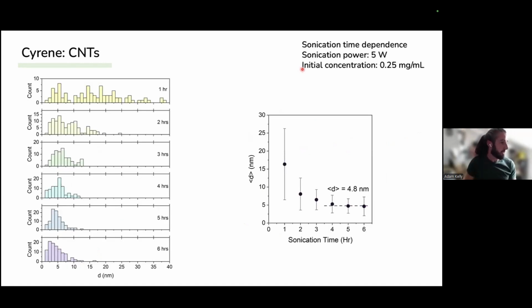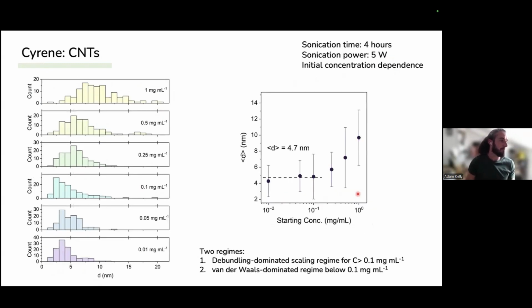So we did a sonication time dependence where we used the same sonication power of 5 watts, and we held the initial concentration constant at about 0.25 mg per mL. We can see as we go up from 1 hour, 2 hours, 3 hours, up to 6 hours, that the distribution of diameters of nanotubes falls off and accumulates around a constant diameter after about 4 hours, and that's about 4.8 nanometers.